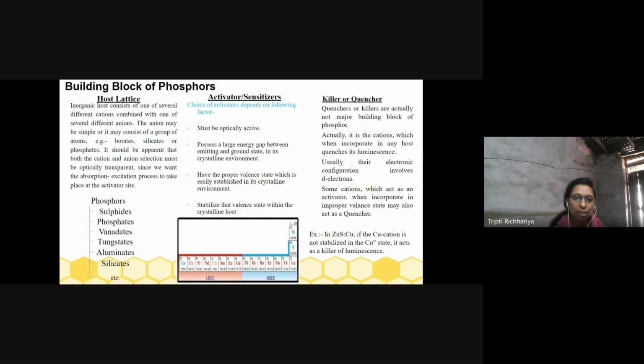The first building block is the host lattice. In general, two types of host lattice are used: organic materials and inorganic materials. But compared to organic materials, inorganic materials are much more used as a host lattice because of their resistive nature towards the environment, because we know that luminescence is structure-based, and as the structure changes, the luminescence properties also change. So compared to organic materials, we prefer to use inorganic materials as a host lattice.